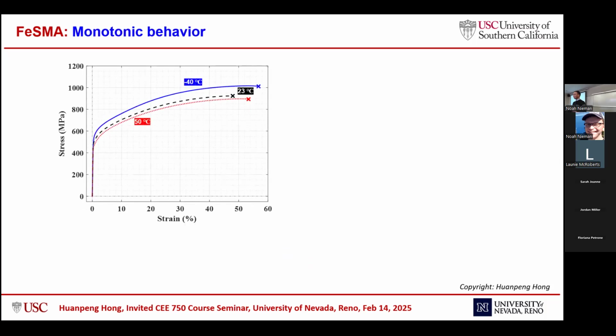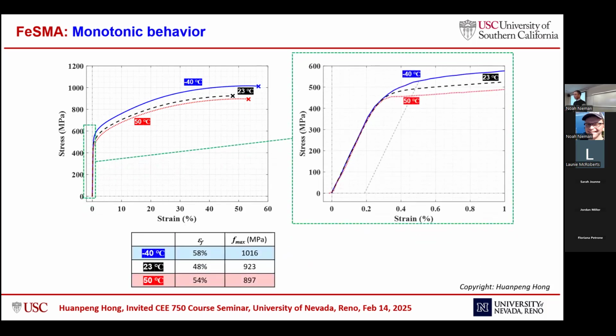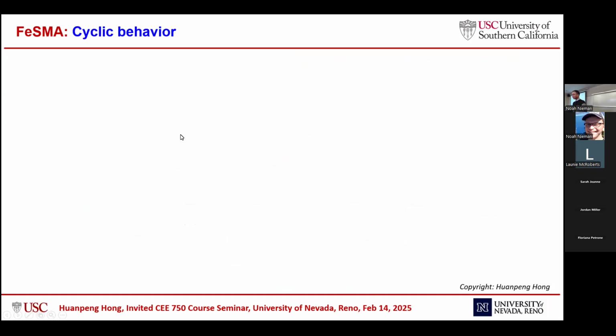So here are some stress strain curves of the iron-based SMA. From these stress strain curves, we see that this material is more like a regular stainless steel. But what is impressive here is that this material is really ductile. The fracture strain can be as high as 50%, and it also works from -40 Celsius to 50 Celsius.